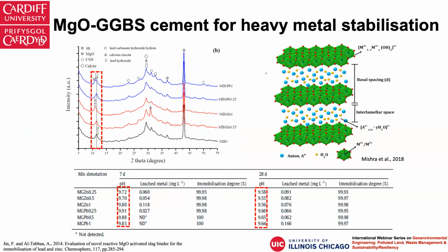And this gives us a crystal structure of this LDH. It is actually a layered structure. Another name of this clay mineral is anion exchange clay. Why it is called anion exchange clay is that in the crystal structure, the divalent ions are substituted by trivalent ions, and then the surfaces are positively charged. So in between, the interlayers are filled with anions, and these anions can be exchanged. That is why it is called anion exchange clay mineral. And all of these divalent and trivalent ions can be substituted by others.